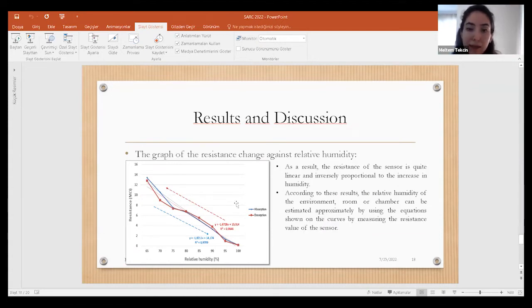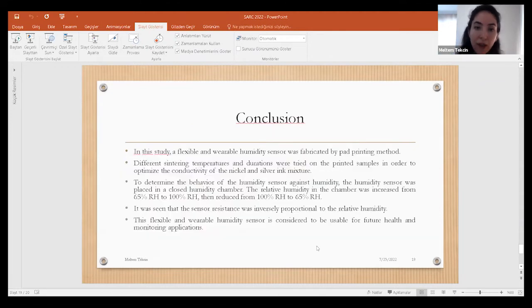As a result, the resistance of the sensor is quite linear and inversely proportional to increase in humidity. According to these results, the relative humidity of the environment, room, or chamber can be estimated approximately by using the equations shown on the curves by measuring the resistance value of the sensor.